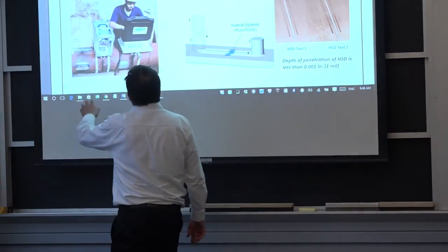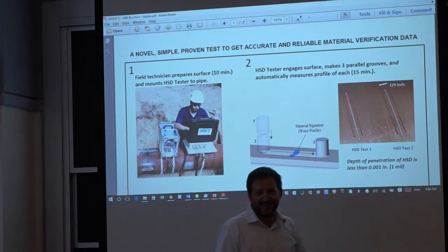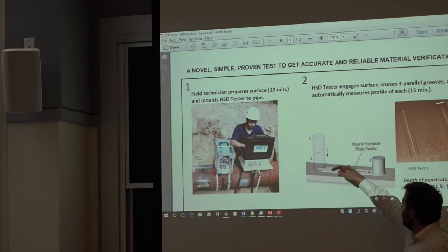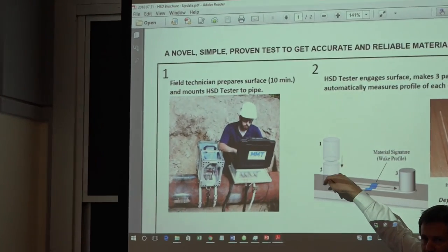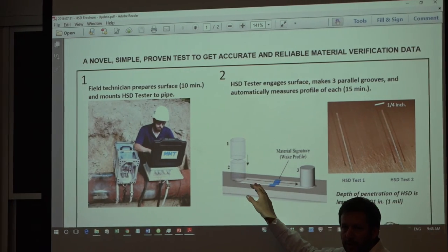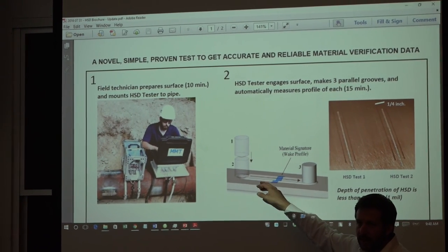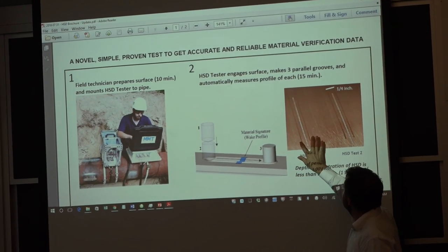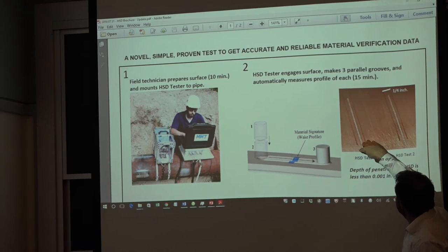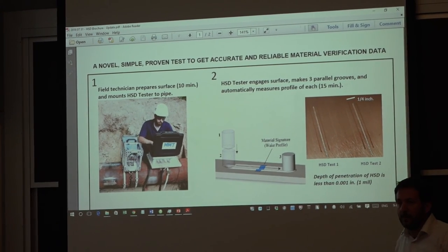So I showed this where we have what we call, some people in the industry call it our fish tank right now because it's just a prototype unit, but it works and it's accurate. So what it does is instead of doing an indentation hardness test on the material, we slide on the surface just like a boat on the river and it leaves a groove behind. We have three of these styluses running over the surface. So this is one test here with three styluses going together, and then we go back and forth and collect the profile information behind it.